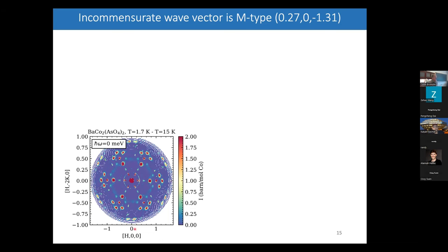So this is the reciprocal lattice basal plane of this material, and I'm showing you elastic scattering, energy transfer equals zero. We see this set of six peaks that surround the nuclear reciprocal lattice point. So this point is a nuclear reciprocal lattice point, this one as well, and this one as well. These are the six points, but surrounding those are an additional six little satellite locations, and those are the peaks associated with this modulated magnetic order.